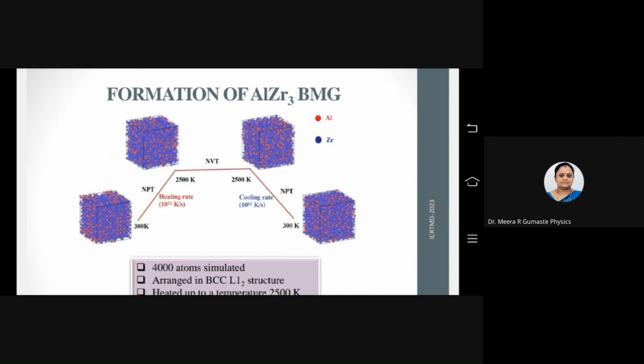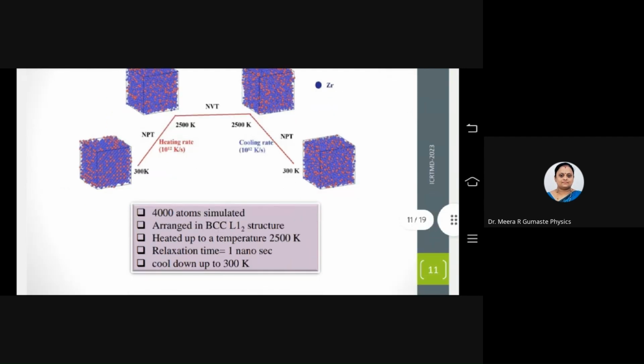You can see here a down arrow in the NPT ensemble to reach the 300 Kelvin structure. So basically the right hand side bottom structure is a bulk metallic glass structure. So bulk metallic glasses are created in that way. That means you heat the crystal at a certain rate, and then you cool it down at a very high rate so that the atoms do not get enough time to crystallize and they form amorphous glass structures. This is what is approached in the MD simulation to get the final structure of the bulk metallic glass of the aluminum zirconium alloy.